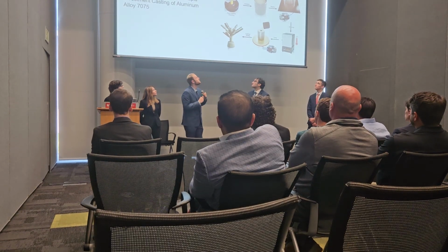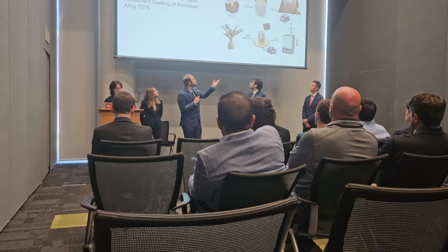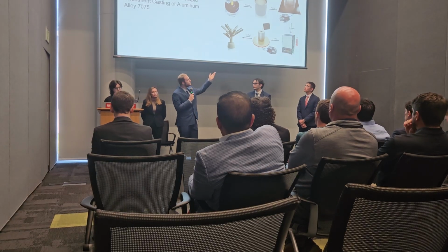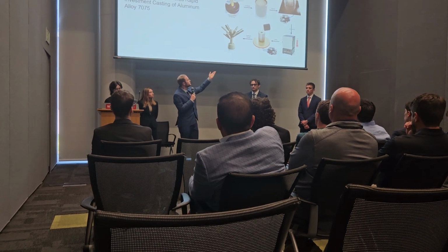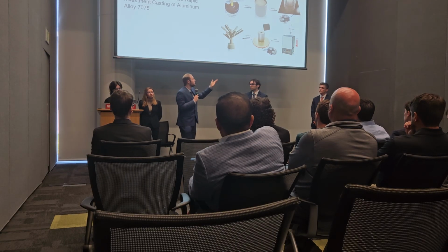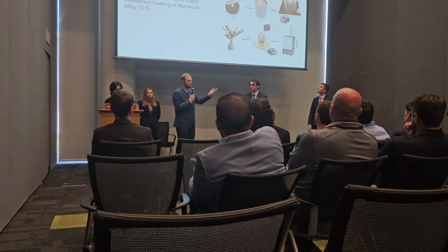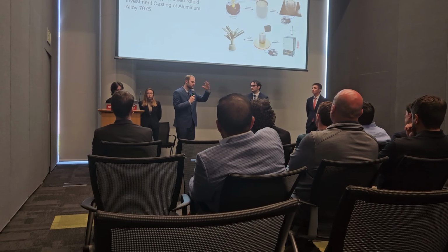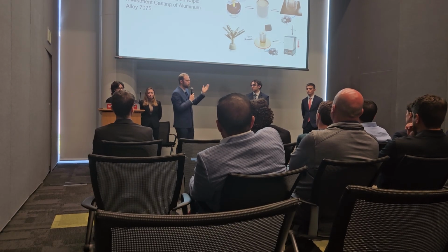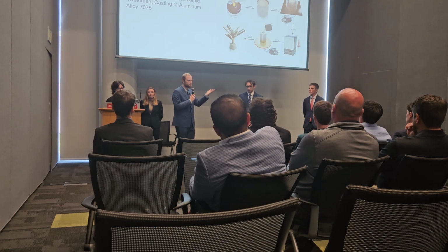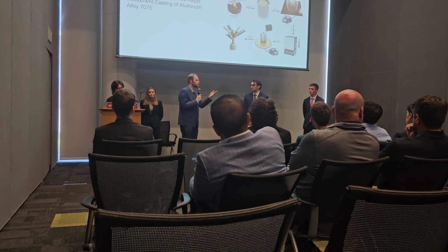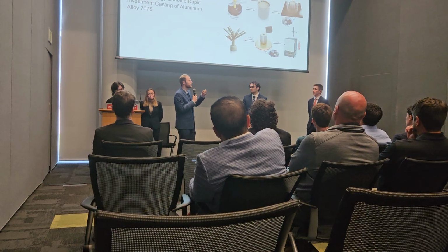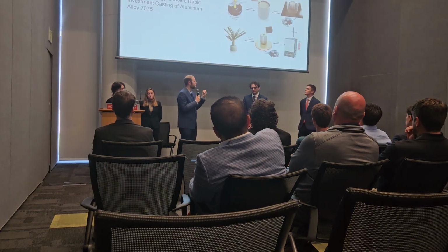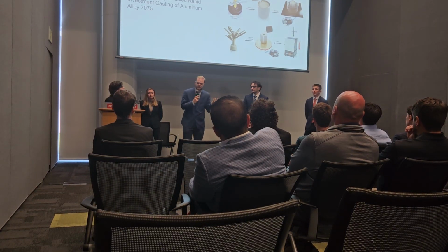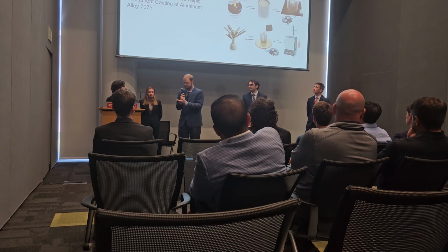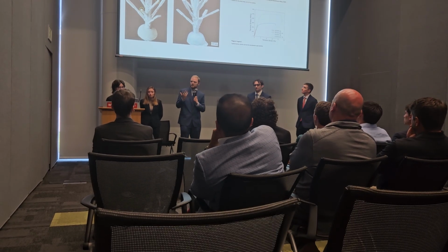Above is the research paper's way of doing it. We mirrored this with CAMEL. Basically, we would have a wax 3D print that we would pour plaster over and then remove any air bubbles through a vacuum chamber. It would then burn out the wax mold, leaving only the formation of the body, and then we would pour in our molten aluminum 7075 with the nano-treated titanium carbide, which allows for flowability and reduces the hot cracking. From there we would remove the plaster casing and machine down our part.